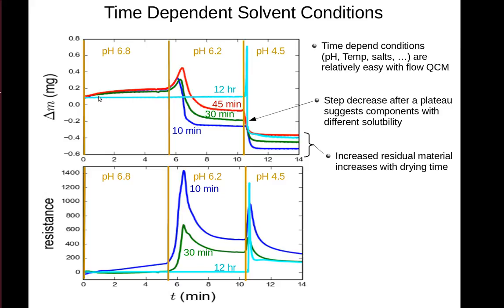Looking at the 10-minute data, we see that at a pH of 6.8, there is some swelling of the polymer. When a step change to 6.2 occurs, there is more rapid swelling, followed by a fairly quick decrease in mass as it starts to dissolve. And then at a pH of 4.5, there's an even faster decrease in the rest of the dissolution of the polymer. This is similar for the 30 minutes and 45 minutes.